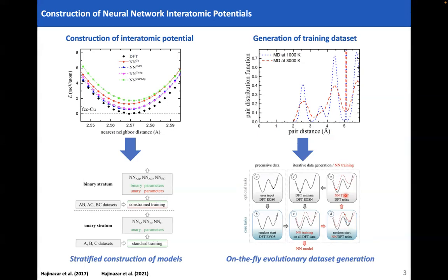for as many iterations as you set up for the whole task. At each stage, you will have a few structures which are not well represented by machine learning. Then you add them to the database, and in the next cycle, the performance of the model will be better. And ideally and hopefully, at each cycle, the number of structures which are not well described by machine learning reduces.